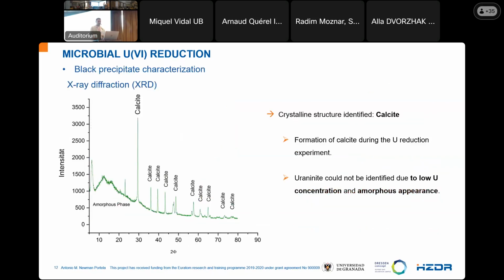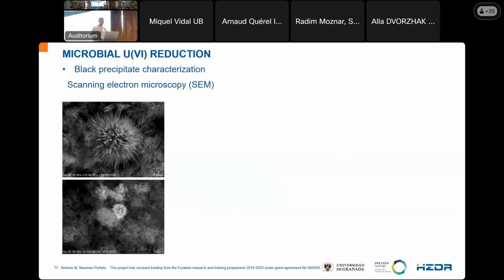Then we use XRD to try to get more information about the black precipitate, but we did not identify uraninite. We identified calcite as the main crystalline structure. Probably we didn't identify the uraninite due to the low concentration of uranium and its amorphous appearance. And when we analyze this sample by scanning electron microscopy, we observe this beautiful calcite structure.